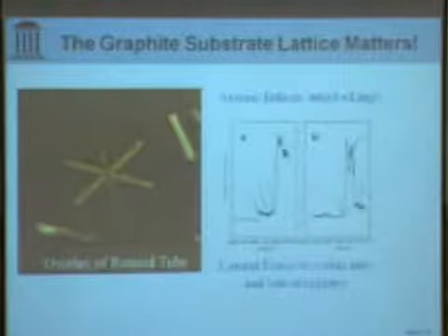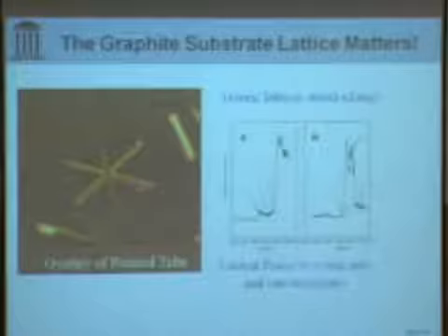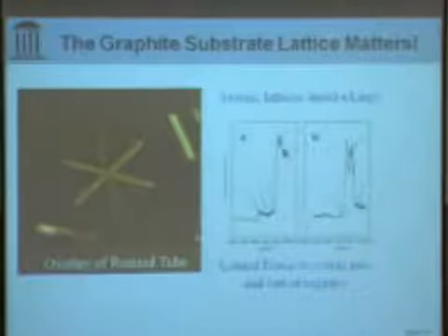These are stable images, and you can see that they line up 60 degrees apart from each other. This is also consistent with when we push a nanotube, the force can be low while the nanotube is sliding, but then suddenly it locks in and it starts rolling. And then the force, curiously, goes up for the rolling. And when we image the tube when it's rolling, it's in one of these positions.